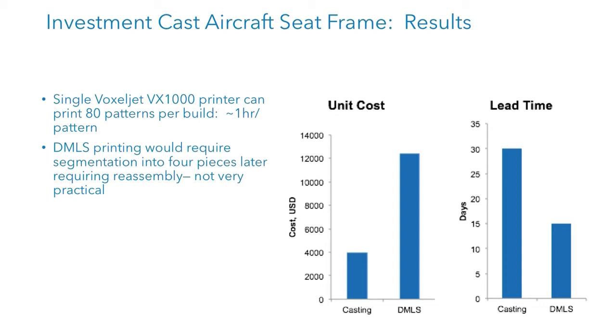Additionally, the general impression in the industry is that casting is a very slow process, and that's only slow when you're cutting tooling. It's actually extremely fast. You can go from printed pattern to part in about 8 hours using some of the modern high-speed investment casting shelling techniques. There are a lot of misconceptions around turnarounds and lead times that are largely holdovers from conventional subtractive processes, which are really the rate-limiting step when you're making tooling for, say, molds for wax parts or tooling for sand molds, which we'll talk about in a minute.